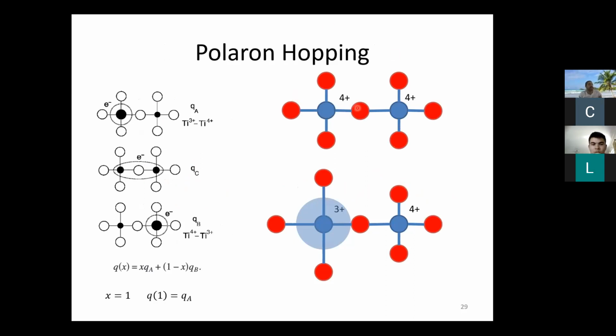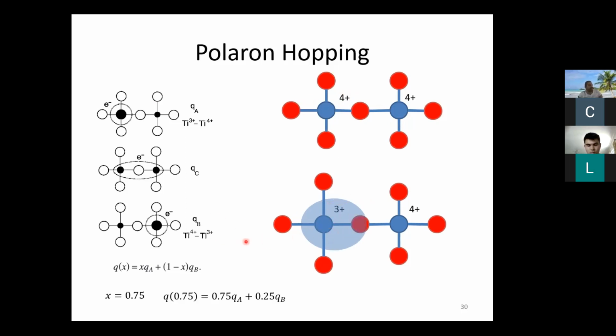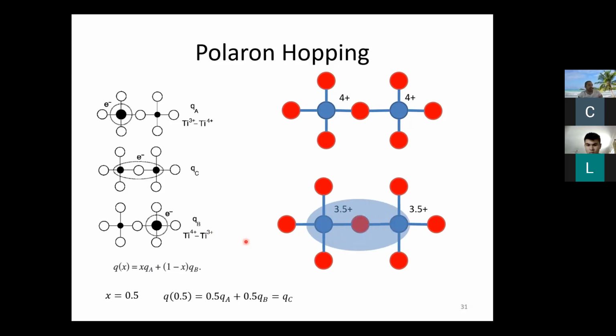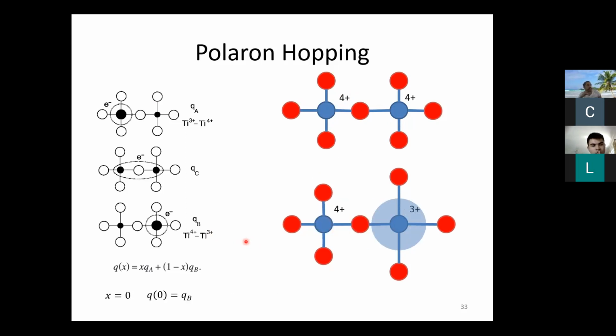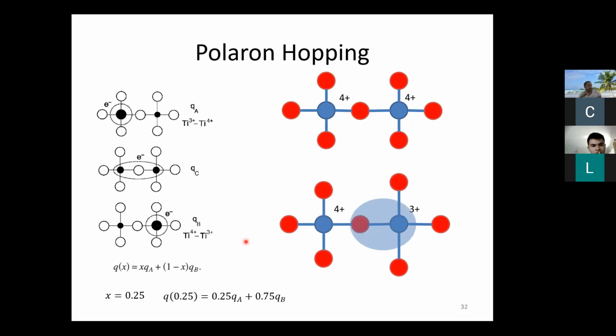Normally this lithium, lanthanum, titanium setup has a valence charge of +4 on each titanium. But if we have a polaron on one, notice I distorted this oxygen further out compared to here. So we have a distortion here. As I move along in each of these snapshots, this electron cloud migrates through, you'd have half and half on each titanium, and then it migrates back to the other one, which is like a little movie.